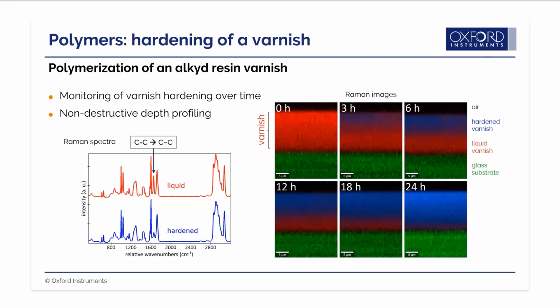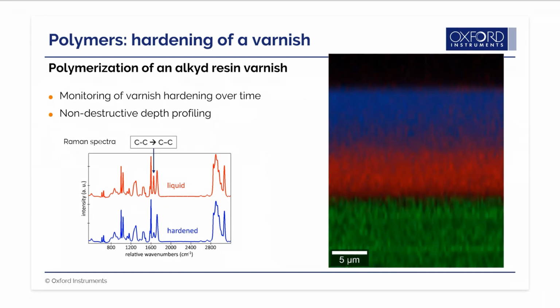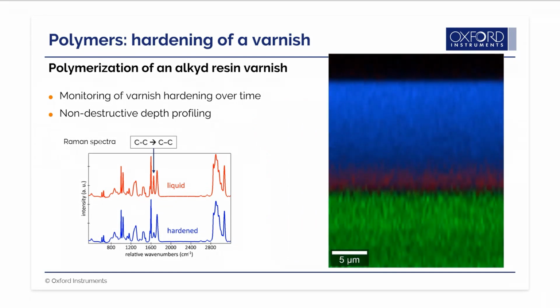In the Raman image, we can see the glass substrate in green, the liquid varnish in red, and the hardened varnish in blue. Over 24 hours, the color changes from red to blue, starting at the surface. The video visualizes this polymerization reaction.